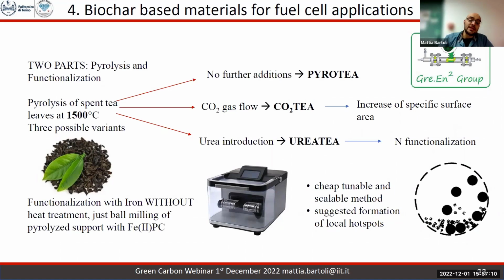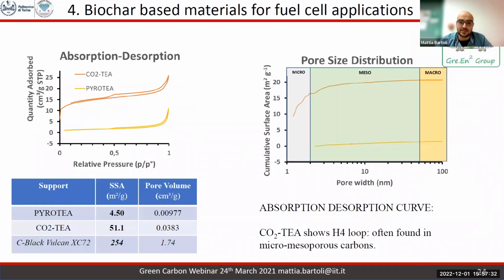This is a weak point because we need a very highly conductive material where we can insert the metal sites by ball milling the precursor that you saw before. Furthermore, in the same step, we also flux CO2 to increase the surface area and insert oxygen functionalities, and we add urea, in a separate step, to insert nitrogen functionalities. And what you can see is that the common theme is low surface area, 4 square meters per gram, so practically negligible. The activated one was around 50 square meters, compared to the common support of platinum, that is carbon black, the Vulcan carbon black, that is up to hundreds. And the pore distribution is also in the mesopore range.